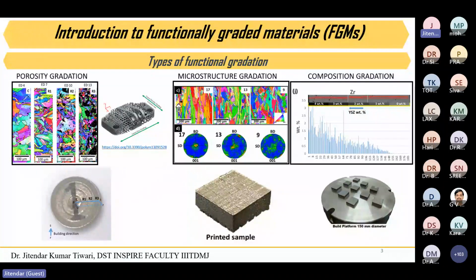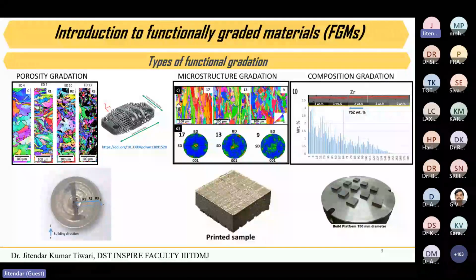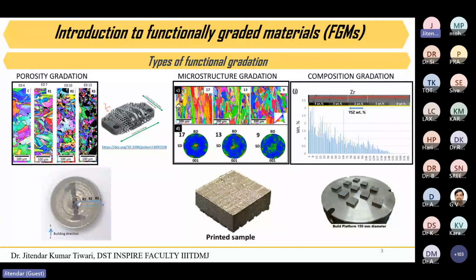But in the powder bed fusion process, if you print a closed cell structure, obviously the powder will get entrapped inside those pores, so laser powder fusion will not be feasible in that case. That is also challenging. Another type is process porosity, and there are three types of it. One is lack of fusion, another is metallurgical porosity, and third, at high energy density there will be keyhole pores. If we change our parameters according to the porosity variation, we can achieve porosity gradation. So that is the first case.